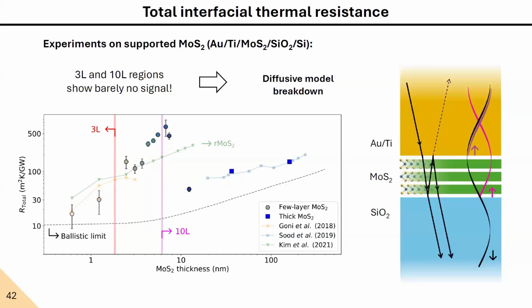Well, I also didn't show you the data for 3 layer and 10 layer regions. And the reason is that these regions show barely any thermoreflectance signal. So we cannot apply our diffusive model to describe these specific regions. So we hypothesize that at specific thickness regions, coherent phonons reflect at the different interfaces and destructively interfere in the backward direction, therefore enhancing our transmission into the substrate.